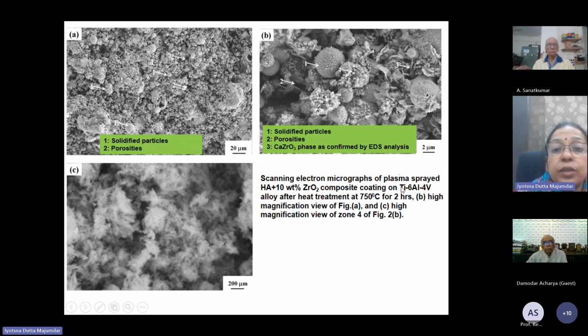This is the scanning electron micrograph of the 10% zirconia composite coating. After heat treatment, at high magnification, a very spongy kind of appearance was observed, because hydroxyapatite reacted with zirconium and calcium zirconate formation took place. These calcium zirconates were also very fine, nanostructured in nature.